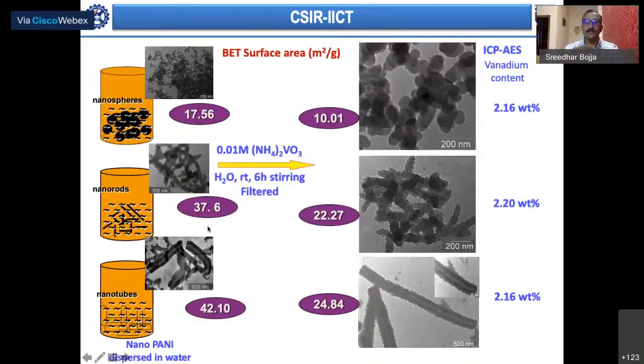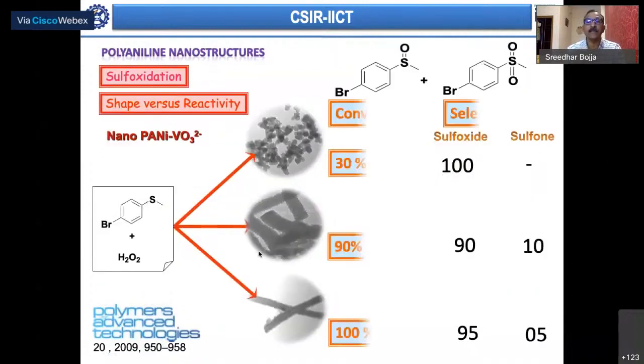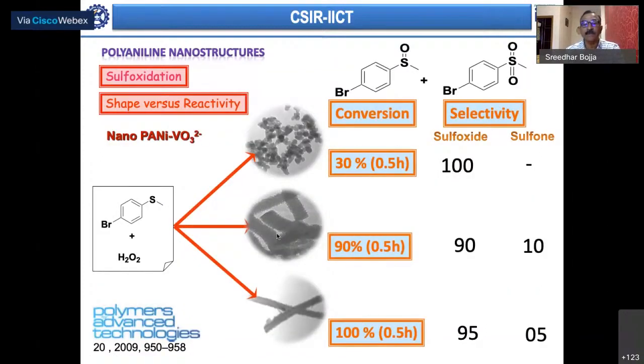So we tried to do all of them, and then we looked at the surface area for catalytic applications. The spheres were about 17, rods about 37, and tubes about 42 square meters per gram. So obviously this tells you they have to be good catalyst supports, and that is what we wanted to prove. We worked on these kinds of reactions and could see that the tubes were better catalysts in terms of conversion or selectivity, and we tried to work on this kind of material.